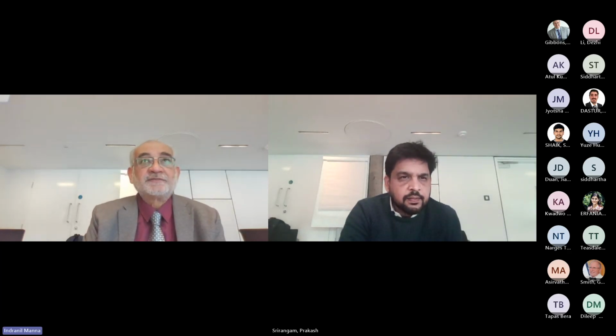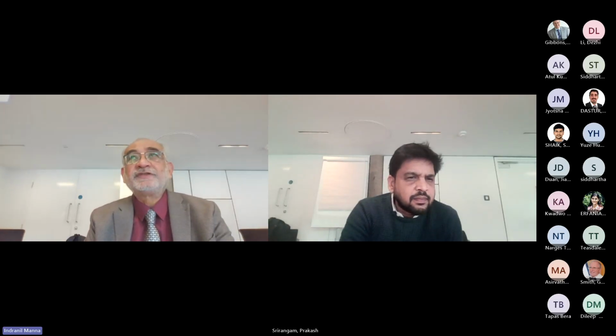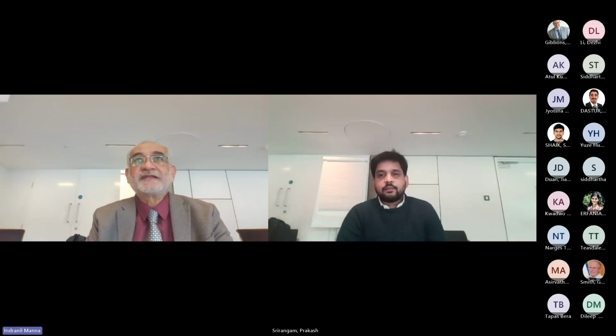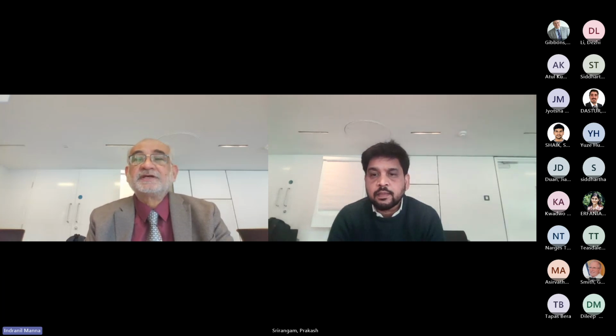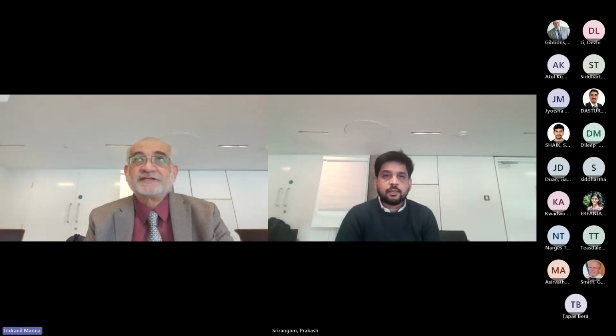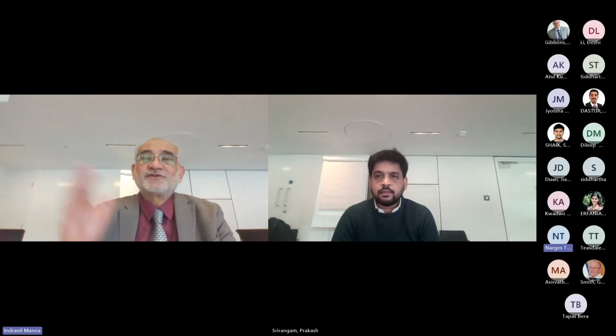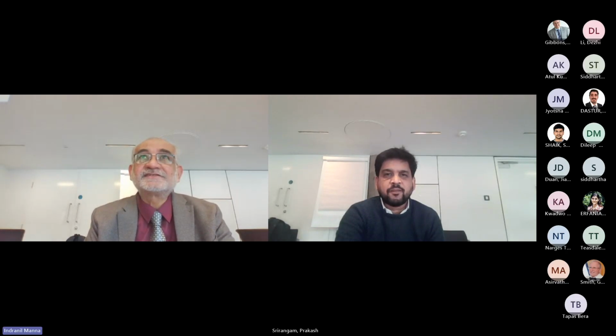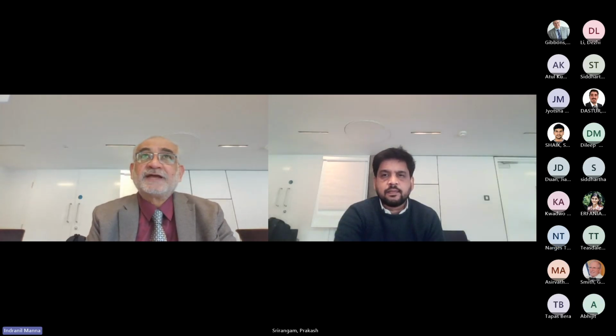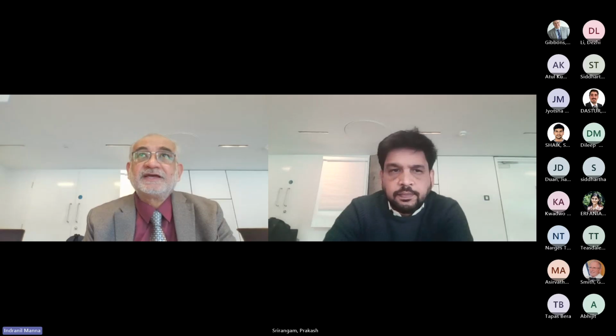No, not in our group at Kharagpur, but we did some trials elsewhere, and I can share my experience. When you have a single crystal of large dimension and you deposit a metallic layer on top of it, there is very little chance you can maintain exactly the same orientation. When the liquid solidifies on a solid substrate, there will be an interface, and across it you'll have tiny little grains. But the advantage is, because of fast cooling, you may retain nearly the same orientation. In other words, the interface need not be a large angle boundary—in all probability it will be a low angle boundary and a directionally grown crystal.